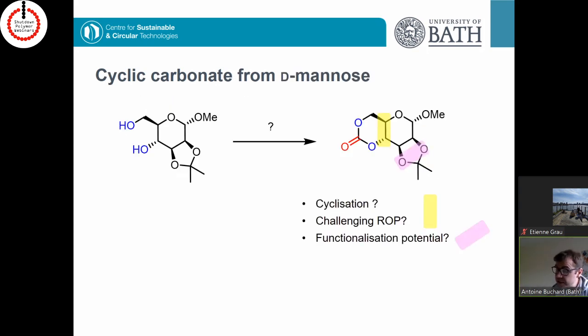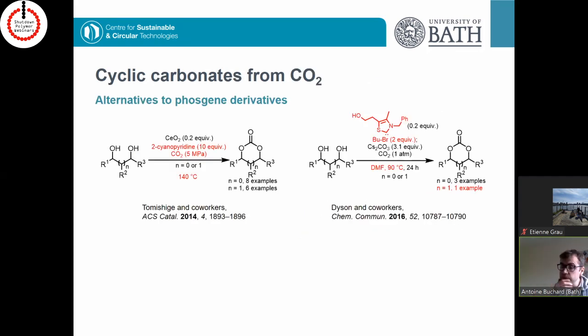The first thing that we needed to do to create this type of monomer was obviously to take this species, which is one step from a commercial product, the O-methoxy derivative, or you can even do it directly from mannose using a 2-step procedure, using methanol with a bit of acid and acetone with a bit of acid as well, which is not very difficult, let's say. And the first thing we wanted to do was to not use phosgene or a phosgene derivative to do this type of chemistry, and we wanted to use CO2 because that was also a bit of our background, let's say.